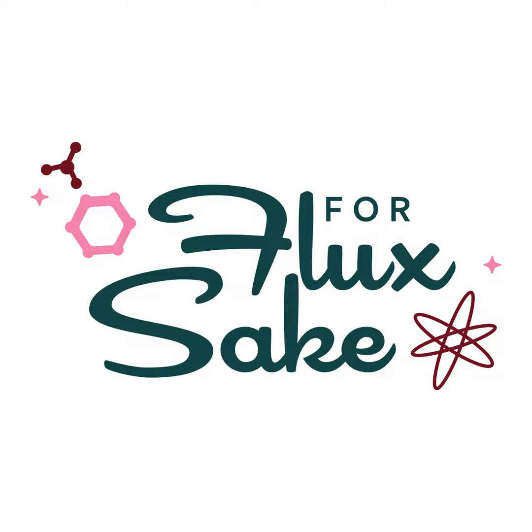And so there's a lot of those really chunky, toothy stonewares that is occurring generally because of the material, fire clays. Fire clays will tend to have a lot of natural iron granules in them, and that iron will bleed through into the glaze, especially if that glaze contains magnesium. Magnesium will tend to really draw them out. So, look for glazes that have dolomite or talc in them, and that'll really help to bleed them out.